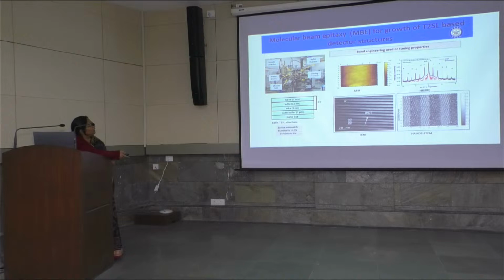Then we also have molecular beam epitaxy. Why I am showing this slide is here you have to grow what we call superlattice layers, 3 nanometer, 0.3 nanometer, and 3 nanometer. And these have to be grown about 300 to 500 periods. This is a strained layer epitaxy in which the strain has to be balanced. So this is a challenge, and then you can see the TEM. You can see the atomically sharp interfaces, and the HRXRD characterization which we do shows enough satellite peaks which speak about the interface sharpness. So these are the requirements which we have for these materials.